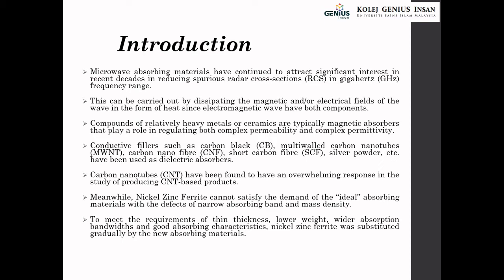Conductive fillers such as carbon black, multi-wall carbon nanotubes, carbon nanofiber, short carbon fiber, silver powder, and others have been used as dielectric absorbers. Carbon nanotubes have been found to have an overwhelming response in the study of producing CNT-based products. Meanwhile, nickel zinc ferrite cannot satisfy the demand of ideal absorbing materials, with the defects of narrow absorbing band and mass density. So what we try to do in this research is mix magnetic material and dielectric material so that we can get suitable permeability and permittivity that can absorb the electromagnetic wave at the higher, gigahertz frequency range.